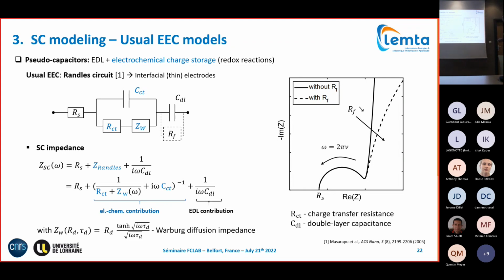It is characterized by a half loop at intermediate to high frequencies that corresponds to your electrochemical charge storage, and a vertical line or steep line at lowest frequencies. Again, according to the leakage, the lower the leakage resistance, the more pronounced the deviation of the low frequency line from the vertical line. Okay, that's the circuit you use.